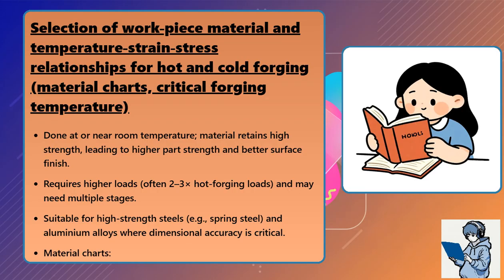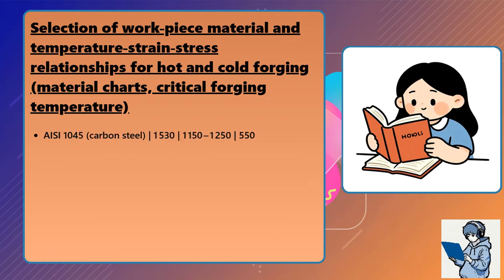Material charts: AISI 1045 carbon steel, melting point 1530 degrees Celsius. Recommended hot forge temperature 1150 to 1250 degrees Celsius. Typical yield strength cold, 550 megapascals.